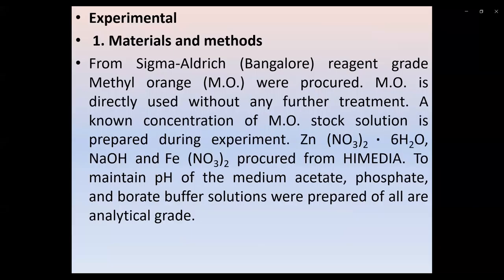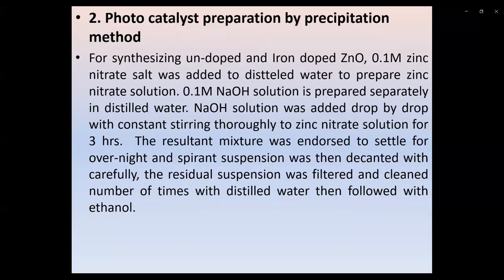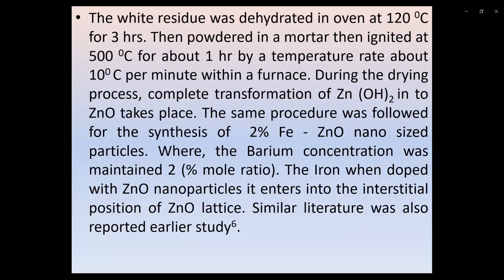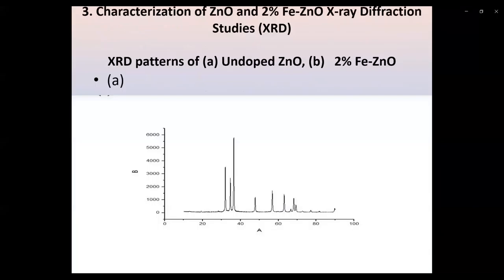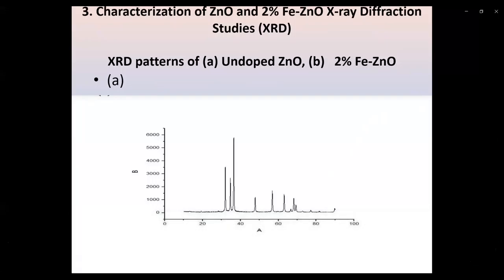So the nanoparticles are prepared by the co-precipitation method by using zinc nitrate and iron nitrate. The photocatalyst is prepared by the co-precipitation method. The particles are heated in an oven at 120 degrees for 3 hours to get the zinc oxide nanoparticles. This slide shows the prepared nanoparticles having the nano size of 40 nm.